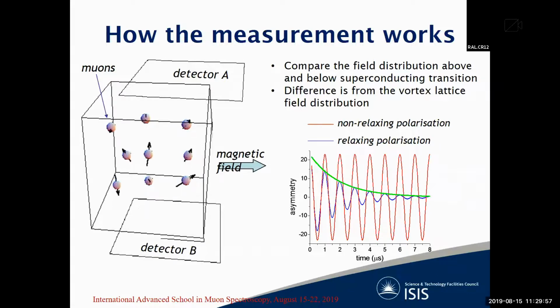Depending on the structure, obviously, in some directions you may have a bigger magnetic shift than in others. Okay. Depending on the shape of the sample and the magnetic field direction, you can have a lesser or greater effect. Right. You usually don't have spherical samples. No. So you normally have a plate-like sample, and if you apply the field along that direction, you'll have a different demagnetization factor than the other direction. Okay. Thank you.